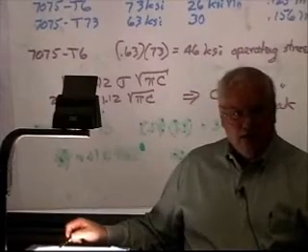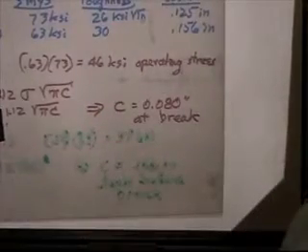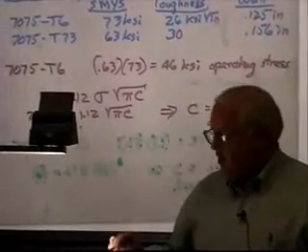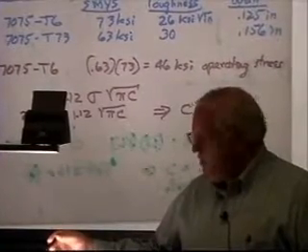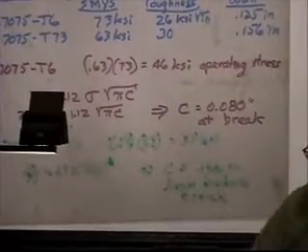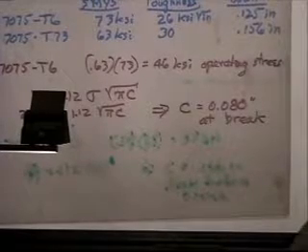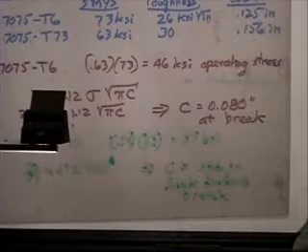And it turns out by doing that, if you go through the stress intensity calculation down here, you'll find that the critical flaw size to break in the original design is about 2mm. You look at that thing, that crack goes about 2mm down. We just verified that these material properties I looked up in a handbook for the original 7075 T6 are correct. And you can't read this very well, but if you go through this, you find the critical flaw size is about 4.5mm. And the thickness is only 4mm, or just under 4mm. That means that you actually get leak before break.